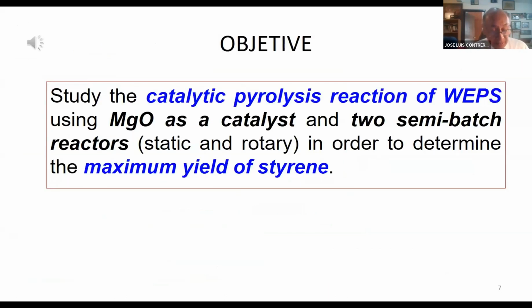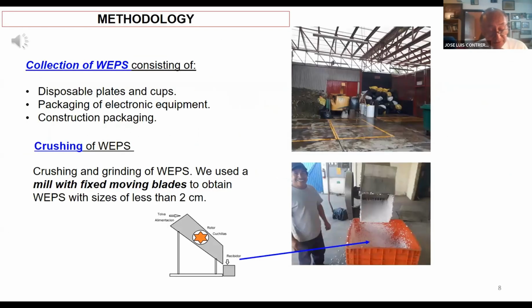The main objective that needs to be achieved in this study is to convert WEPS into styrene with a basic magnesium oxide catalyst using a rotary reactor. The WEPS collection consisted of waste plates and disposable cups, electronic material packaging, and other types of packaging. In the case of crushing and grinding of WEPS, we use a mill with fixed moving blades to obtain WEPS with sizes of less than 2 centimeters, as can be seen in the photograph.